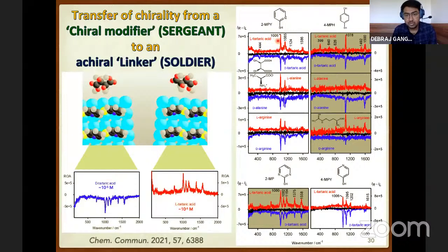So we have primarily used 3 chiral modifiers: L and D tartaric acid, L and D alanine, and L and D arginine. So these we have used as chiral modifiers, and you can see this chiral modifier can align it to the dextro or the levo form. And what we observe is not the surface enhanced Raman spectrum from the chiral molecule, but it's from the achiral linker. But for the different chiral modifiers, the D and the L, we get mirror image spectra. And the CID ratio is very high.